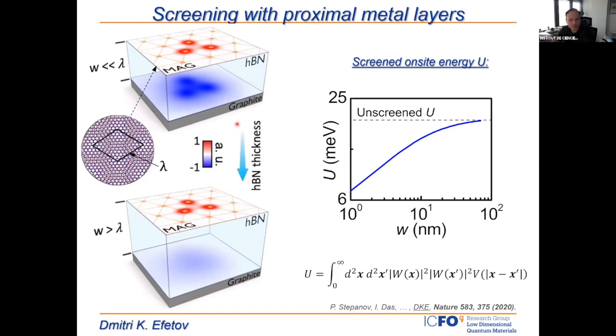And really, we were wondering what is the length scale? How closely can we bring this metallic graphite gate to the magic angle graphene such that the screening affects the U in a more pronounced way? And this is the calculation by Leonard. Here he calculates just U as a function of this gate distance. And for above like 30 nanometer distance, we really don't observe any change. But with a characteristic length scale below 15 nanometers, U becomes really dramatically screened out. And this length scale, 15 nanometers, is really just the size of this Wannier function in the magic angle graphene. So this is just the size of the moiré unit cell itself.